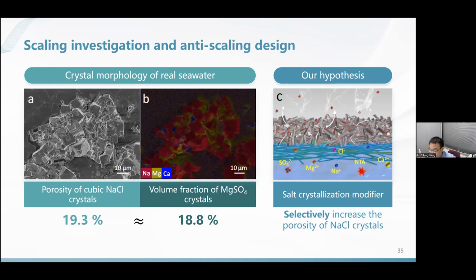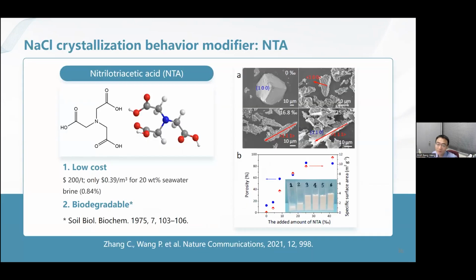Now, that's our hypothesis. Based on this hypothesis, we also have a theory. If we are fortunate enough to find a chemical that, when added to the raw brine of the real seawater, can selectively change or enlarge the porosity of sodium chloride, let's say it enhances the porosity from 19.3% to 50%, then the troublemaker, magnesium sulfate, will not block all of the pores. So when you have such a chemical, you should be able to solve this very tightly packed crust formation issue.